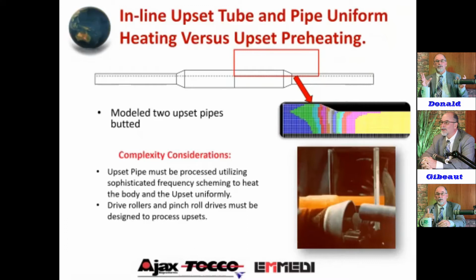The traditional way to process upsets was to preheat the leading and the trailing end. But when you do that and you put it on the line and you've got a 48-foot long pipe, you end up with a differential between the ends and the body. So through FEA analysis, as we were showing here, we were able to come up with what we call frequency scheming for upset tubing, where we can actually heat the upset first, that thicker mass. Remember, we said the lines of flux we can separate by frequency. And we use that to heat that thicker mass.